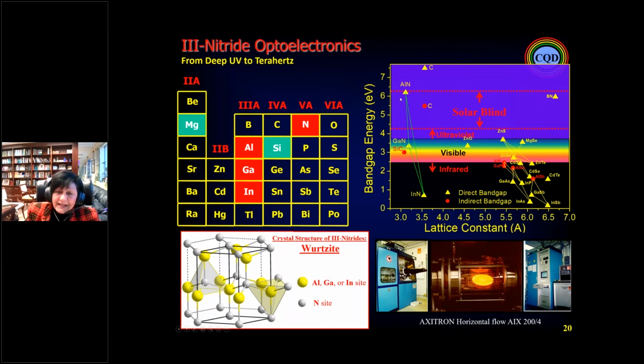But the most important part is this: you have to know that still, after 50, 60 years, nobody can make the substrate in aluminum nitride or gallium nitride, despite many different efforts. So that is another subject of research for the future. But the best substrate for that is sapphire, aluminum oxide, that is wurtzite and has approximately the same, rather similar, lattice parameter. So it was immediately the aluminum gallium indium nitride, this quaternary, and they have the wurtzite structure.